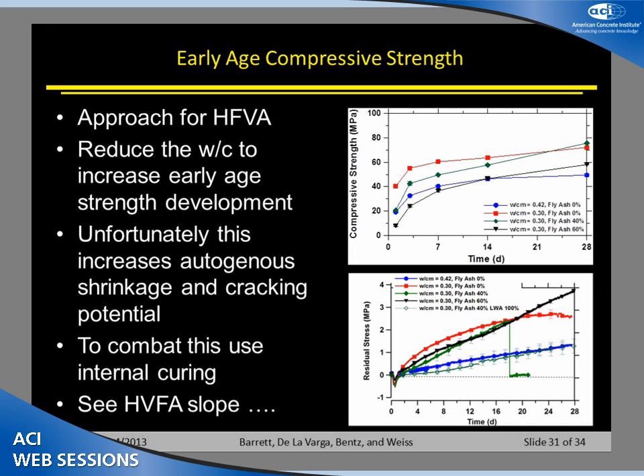Very similar performance around 7 days if we're replacing 60% of the cement inside the overall system. Now, normally this becomes problematic if you drop the water to cement ratio that low because you lead to cracking problems and other things like this. But this is really one of the benefits of the internal curing.